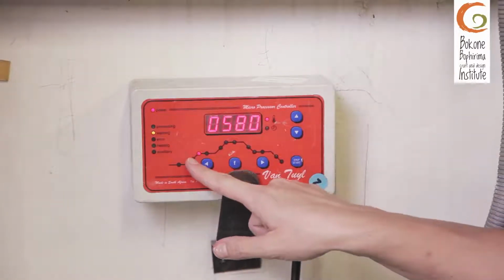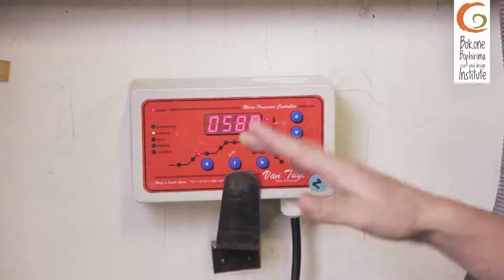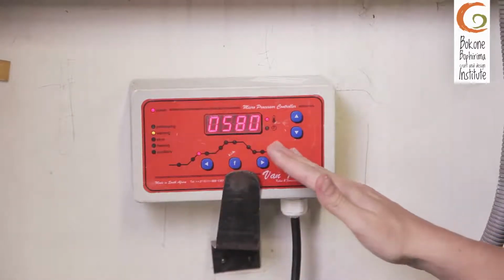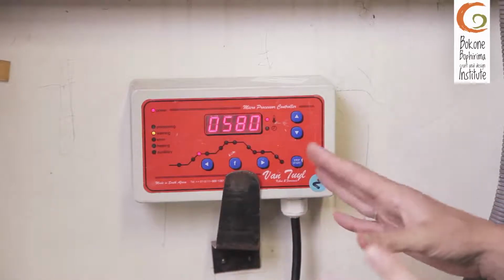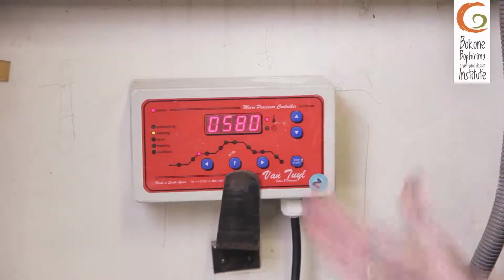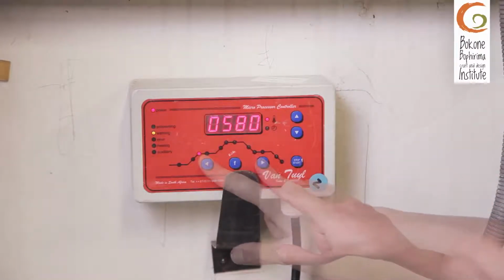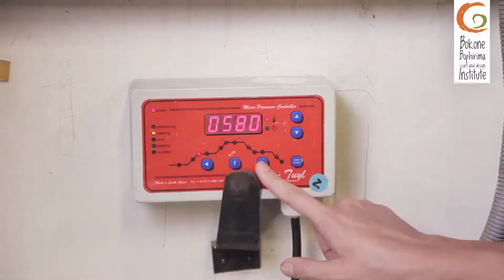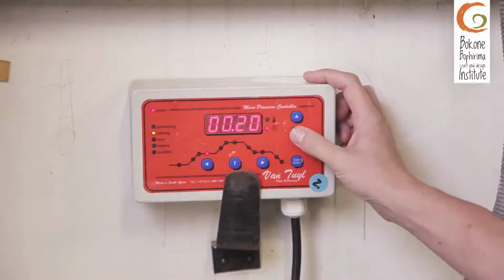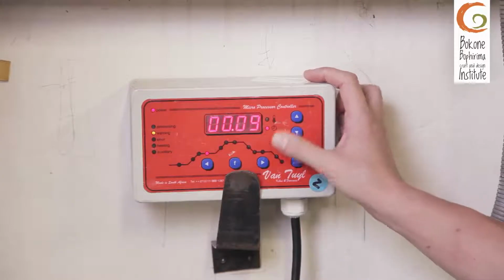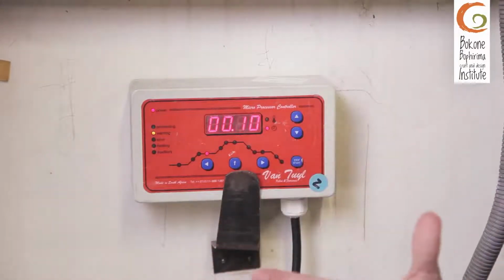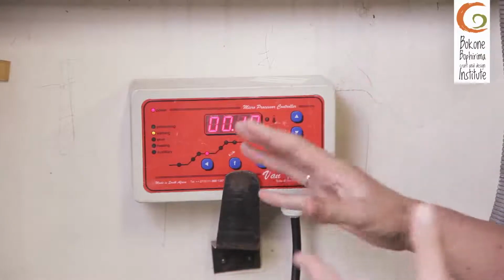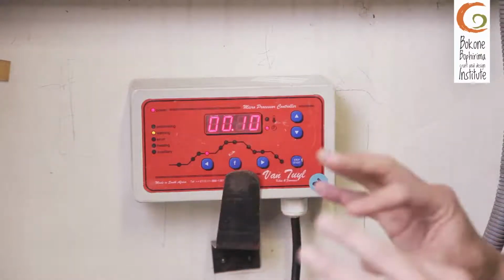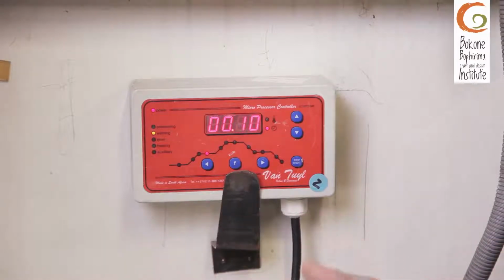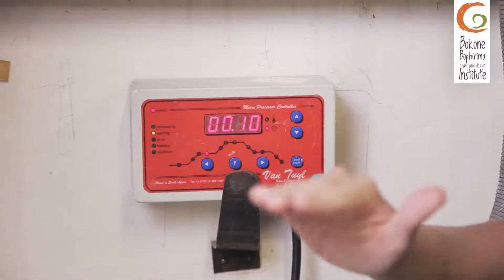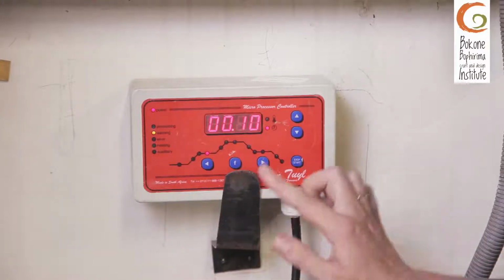Okay, our next section where we're going to allow our glass to soak is at 580. Anything between 60 and 580, our glass is under stress. So it's a point where we want our glass to go up slowly or go down slowly. So always keep that in mind. So now we're at our midpoint of 580, and I'm going to now put a soaking point of 10 minutes in. Our glass is not that thick, so we don't need it to allow it to soak for that long. So that why we put a soak in is to make sure that our glass, the entire, not just the top surface, but the entire, from the bottom to the top, has evenly heated up in between.